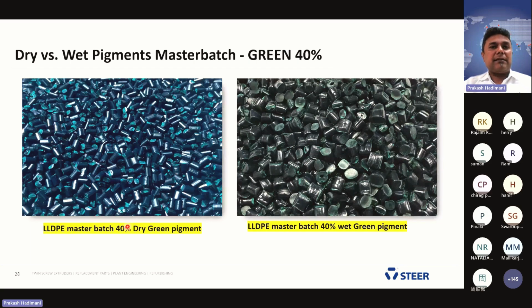This is again 40% dry pigments with LLDPE. This is a pellet. And if you see the right hand side, LLDPE, 40% masterbatch green pigment, wet pigments. When you see the pellets, smooth surface and shiny surface, no additives, no waxes used in this. And if you see the surface, the pigment was completely dispersed into the polymer matrix.